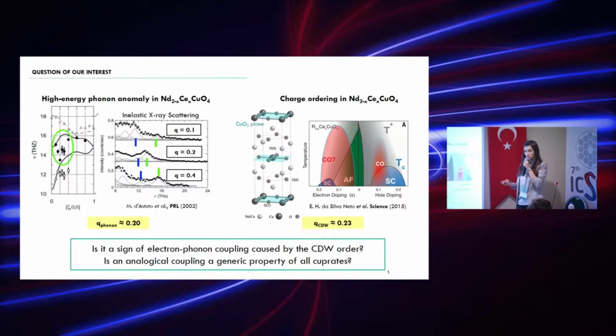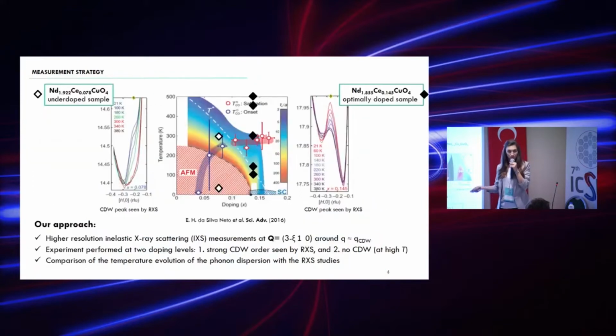So what we did was to redo this experiment and make it for different temperatures and dopings, also for the same compound, neodymium cerium copper oxide. Why this compound? Because it's a very simple one with one copper-oxygen plane per unit cell, and another advantage is that for this compound charge order appears over a very wide range of temperatures and dopings. So it's quite easy to follow charge order in this compound.